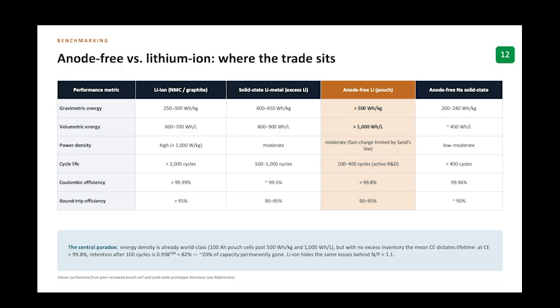So now let's benchmark anode-free systems with lithium-ion batteries and see where the trade sits. Speaking of gravimetric energy and volumetric energy, we have lots of improvement. As you see, 1000 watt-hour per liter for volumetric is what aviation systems like to see if we want to move to energy storage systems for powering them. But on power density, we still need to improve because we are on the moderate side, and lithium-ion batteries are on the safe side with above 1000 watts per kilogram. The other thing that needs to be improved is cycle life, which is at most 400 cycles with the current active R&Ds. But lithium-ion batteries are above 2000 cycles with coulombic efficiencies above 99.99% and round trip efficiencies above 95%.